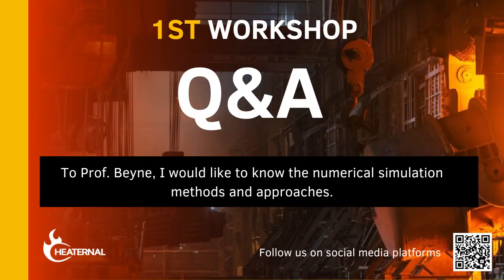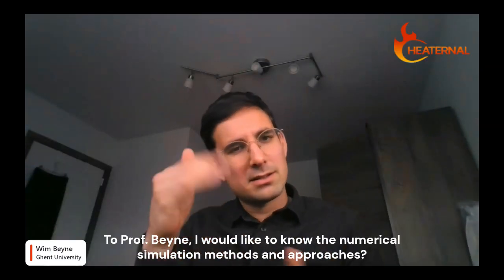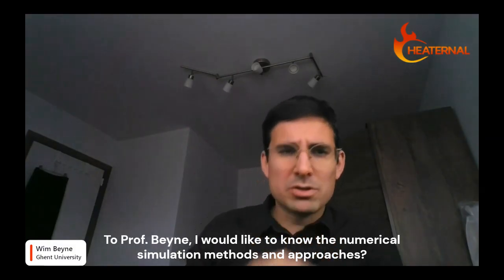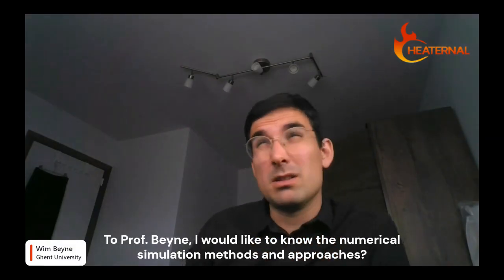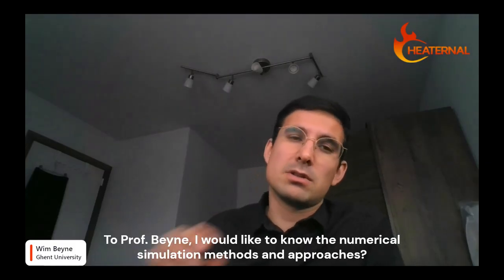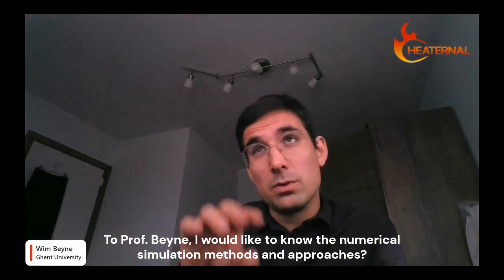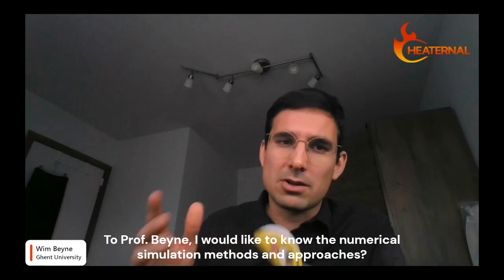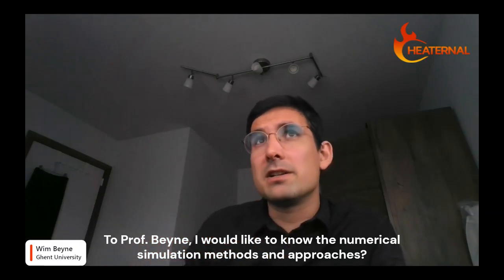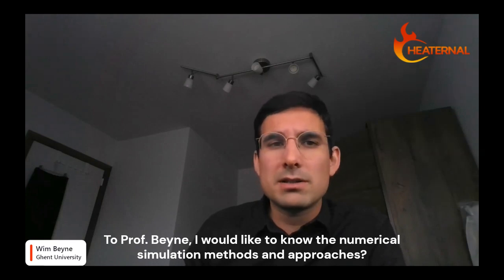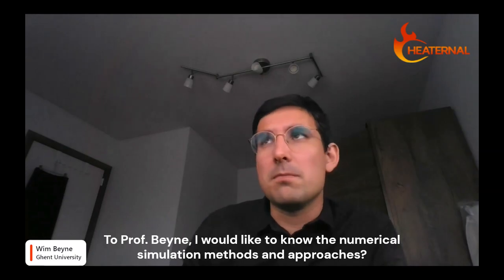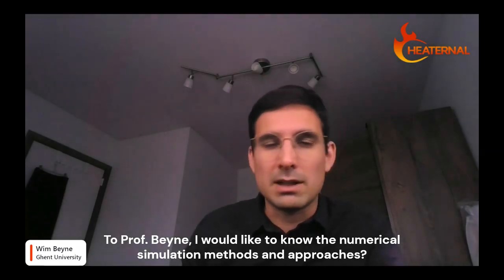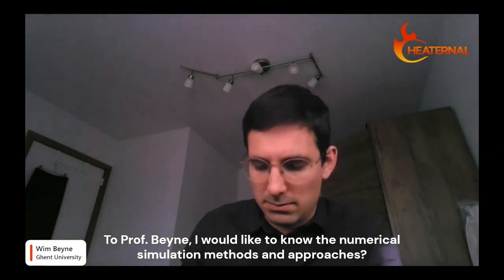I see one last question to Professor Beyne. I would like to know the numerical simulation methods and approaches. Okay, so as I said, there are different levels we're using. The most complex level uses finite volume, with at a certain point a CFD resolved air channel. And then we solve energy equations in the refractory and the PCM, so it's a conjugate heat transfer problem. In the phase change material, we didn't solve the flow equations because the thermal conductivity is so high that we don't see an effect of natural convection on the overall performance.